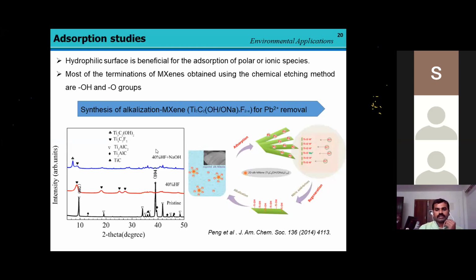Initially, with the help of the Gogotsi group, they started with the introduction of sodium ions into the basal plane of this MXene. Then it forms a sodium form, an alkalinization form of MXene, utilized for lead ion removal. They confirmed that the sodium ion was intercalated rather than forming an upper layer. This intercalation between the layers was confirmed by PXRD studies.